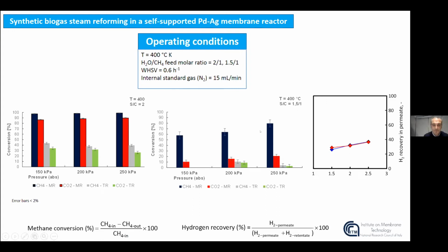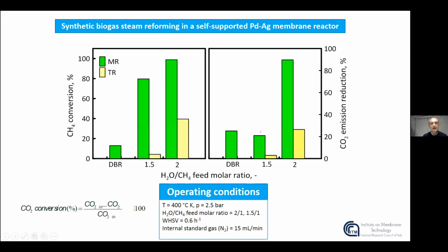In this slide, I would like to show you the conversion of methane in the membrane reactor and the conventional reactor as a function of the feed molar ratio. In this case, it's possible to observe how the membrane reactor performs better than the traditional reactor. The higher the feed molar ratio, of course, the higher the conversion in both cases, because the higher the steam amount with respect to the methane, the higher the conversion, but the conversion in the membrane reactor was higher, up to almost 100%.